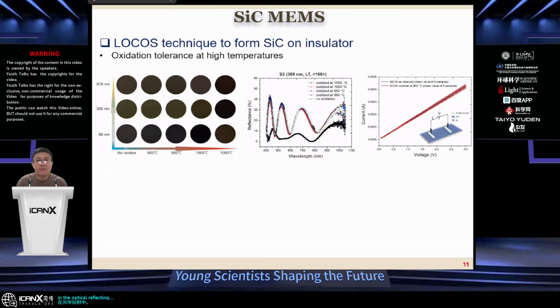And we also confirmed that with electrical properties. We oxidized the material at 1,000 degrees C for an hour. And after that, we measured the electrical conductivity. It retained the excellent electrical conductivity after the oxidation test, meaning you can use the material around 1,000 or 950 degrees C.